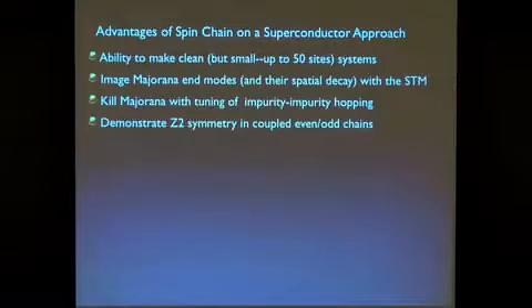But let me tell you what's the advantage of this technique. So obviously you can make very clean structures. You can make crystals of niobium. Niobium is actually difficult. Lead is probably a little easier. Very, very clean. And you can assemble chains up to 20, 30 atoms, no problem. And of course, the power of what we are doing is imaging. We can go to the end of the chain and make sure this zero state is really associated with the end of the chain.